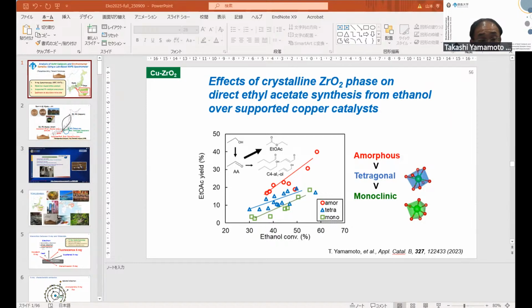But we found the catalyst selectivity is different and depends on the crystalline phase of the zirconia. We found the amorphous type catalyst gives the best ethyl acetate yield and selectivity, but the monoclinic catalyst has worse selectivity. The crystalline phase dependencies have been reported by other research groups, but the tendencies are quite different. We prepared more than 30 kinds of copper zirconia catalyst using the same raw materials, so we can conclude the amorphous catalyst is best.